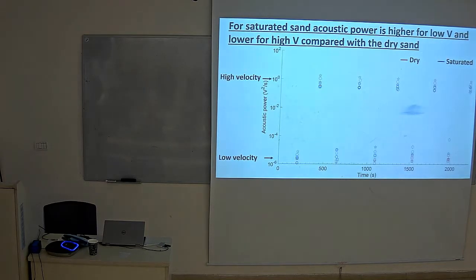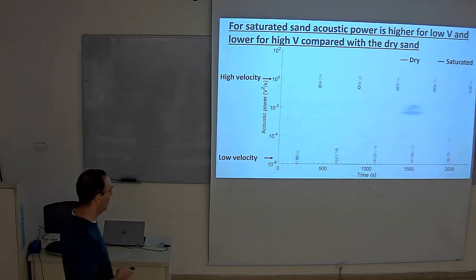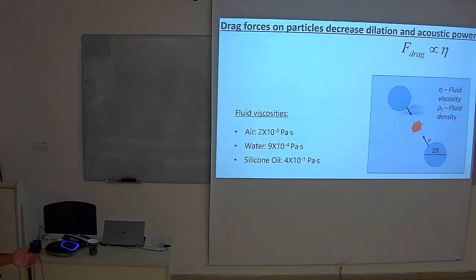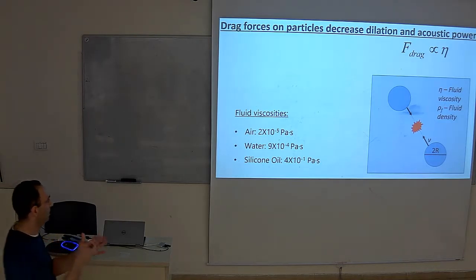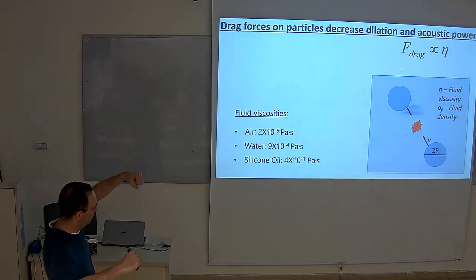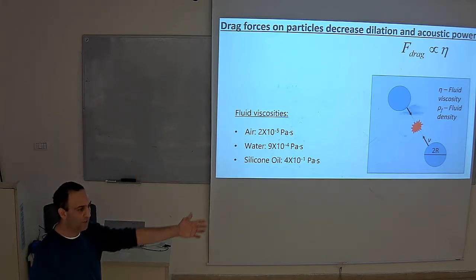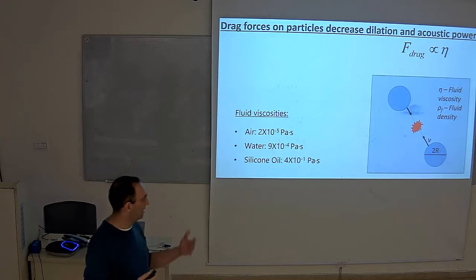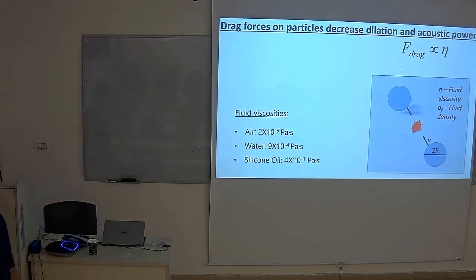So these are very noisy signals. In order to summarize it, we look at the acoustic power, which means the square of the amplitude of the waveforms. This is the high velocity, this is the low velocity, versus time. And what we get is indeed that the high velocity dry experiments have more acoustic energy, which is different from low velocity, where they have less acoustic energy. So the explanation for it may be, as I said, just the drag force on each particle. When the two particles are moving toward each other, they now have a fluid, water, there, so the viscosity is higher than air, and therefore they collide with less velocity and less energy.